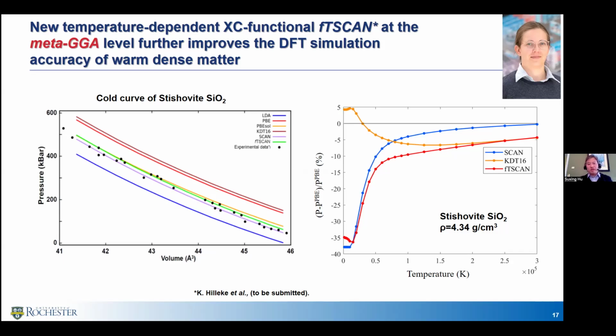But what Katie is showing here is this finite temperature SCAN can give you a better agreement with the experiment measurement, compared with this low level PBE or others. So this is zero temperature. But what we're trying to do is even the finite temperature, when you get it to the zero temperature limit, it should recover this so-called SCAN, which gives you a better agreement with the experiment.